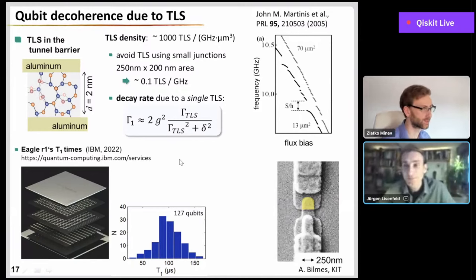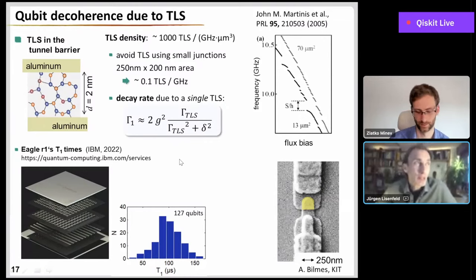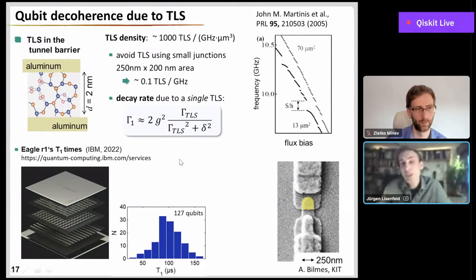Okay, so 100 nanoseconds, you've seen up to 10 microseconds, and maybe there are things at milliseconds, but we don't know too much. We really don't know so much, and I'm not aware of any good results that show that these defects could really have such longer lifetimes. There's a recent publication by Martin Schwicker, also from the KIT group, who did see some very long time effects in fluxonium qubits, and so this is actually a hint that there may be defects or some other states in the environment of these qubits which may have a longer lifetime or longer relaxation rates, but for these defects which I'm at least studying here, this is a reasonable number to quote.